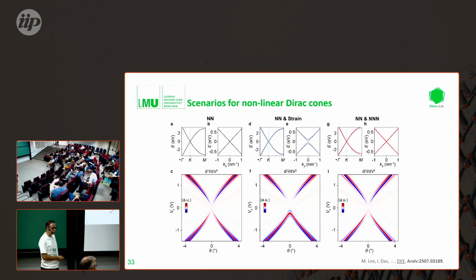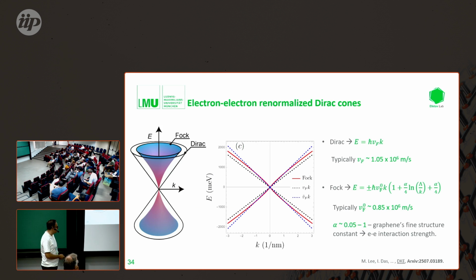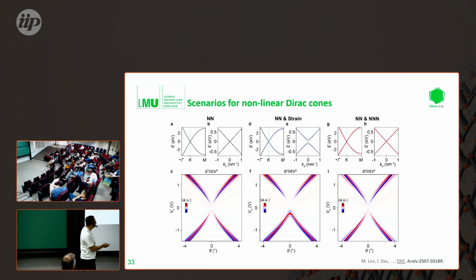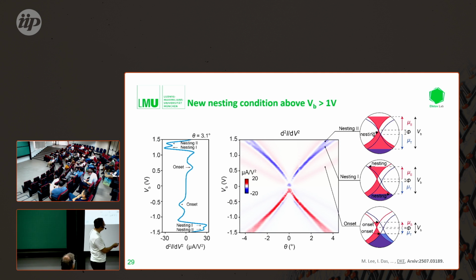So maybe this is the way to see it. There's a small correction, which is enlarging the Fermi velocity here, and then making it smaller again. So this is the correction that we see. If you start overlaying those two band structures on one another and trying to see where they become parallel with one another, you will find that there are two nesting conditions which are separate. And this is something which one can best explain by looking at these type of scenarios here.